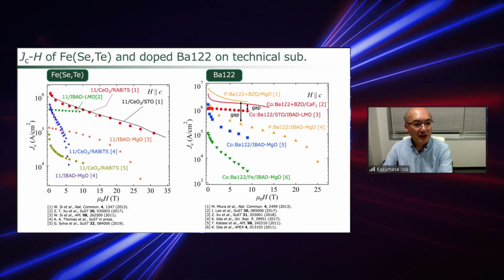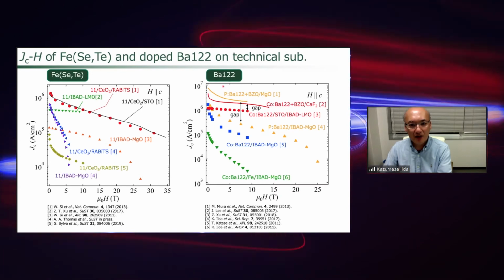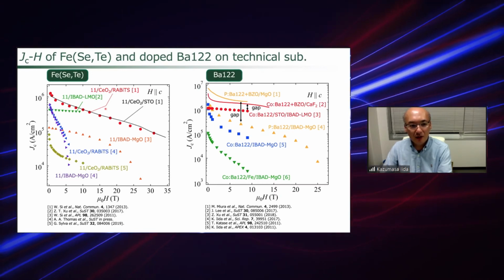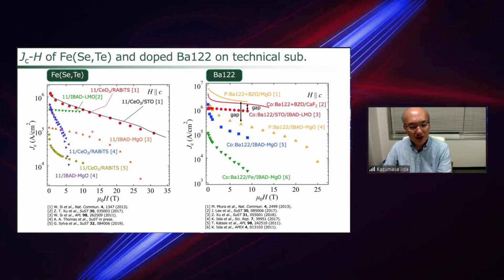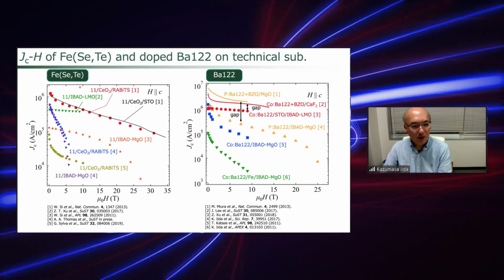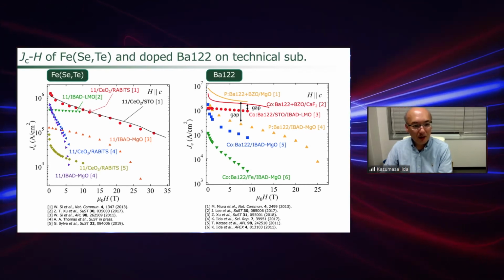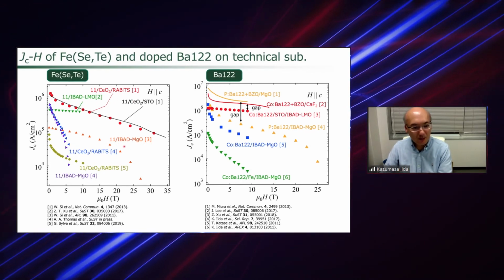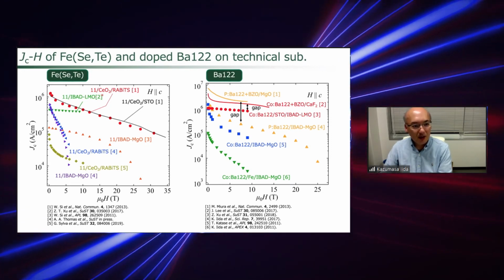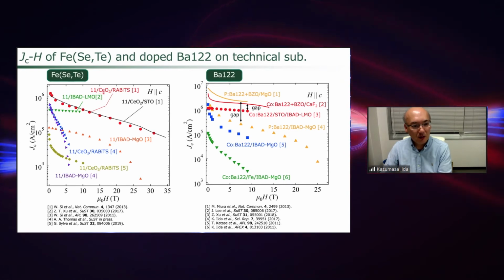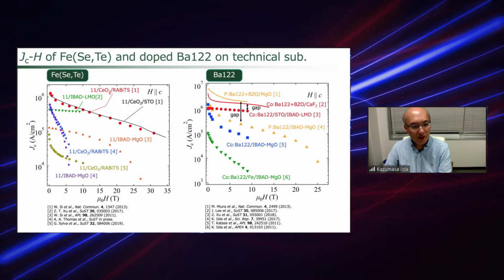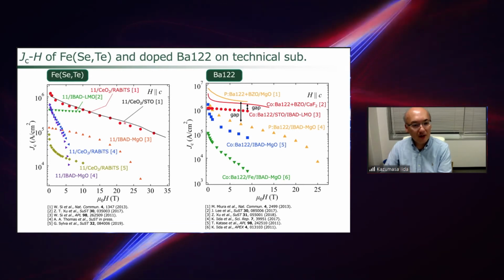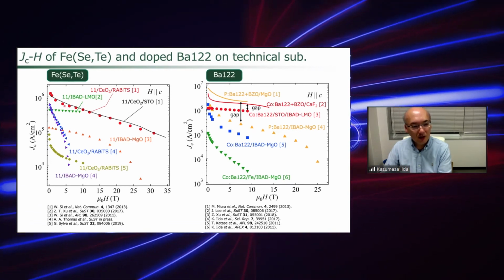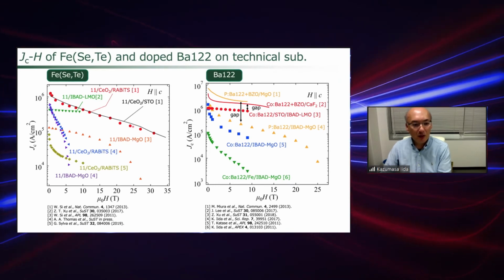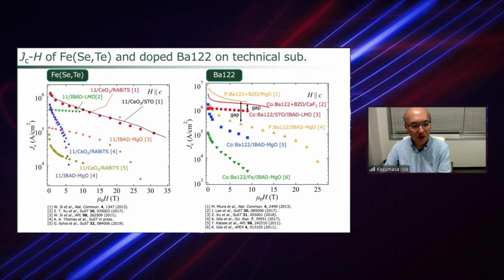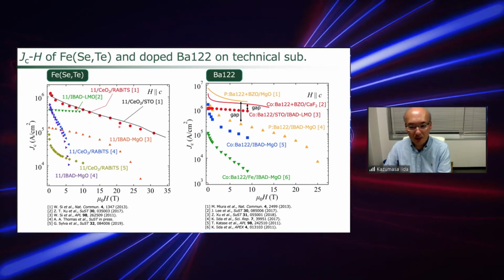And here is a summary of the iron selenide and the barium 122 films grown on the technical substrate, as well as the single crystalline substrate. For the 11 systems, RABiTS templates and also the IBAD templates both have been used. Especially in this case, the 11 grown on the CeO2 buffer, the RABiTS template shows almost the same properties as the film grown on the single crystalline substrate. That means the performance gap is almost negligible between the films grown on the technical substrate and the single crystal substrate.